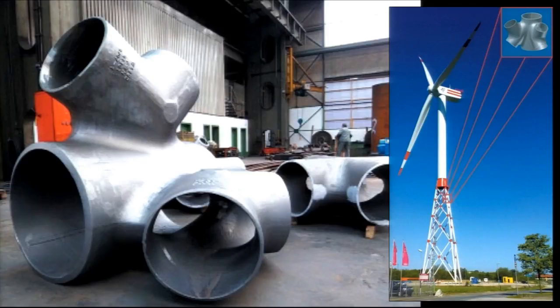So here you see a cast node that's used in an offshore wind turbine basement structure. And the purpose for this connection is to improve the fatigue performance of the overall structure. So as you're looking at this cast node, you can appreciate that you can't make a monolithic structural steel component of that geometry using any other manufacturing technique but steel castings. I can't roll and bend and weld plate work to make that geometry. But it's not just a geometry and it's not just a shape. This node in this structure makes the total life cycle of that structure 10 times longer. So that connection can resist 10 times the number of cycles than a conventionally fabricated connection would otherwise be able to carry.